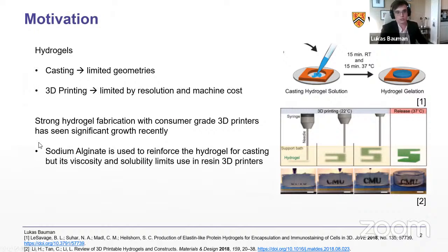Okay, good. So the motivation for this is typically hydrogels are made through casting, and this is an issue as you can get strong hydrogels, but the geometry is very limited. And we also saw a previous presentation in this group on functional composite materials where they did 3D print hydrogels. But part of the issue with the original extrusion 3D printing is they're more limited in your resolution. And typically with 3D printing, you also have weaker hydrogels compared to casting.